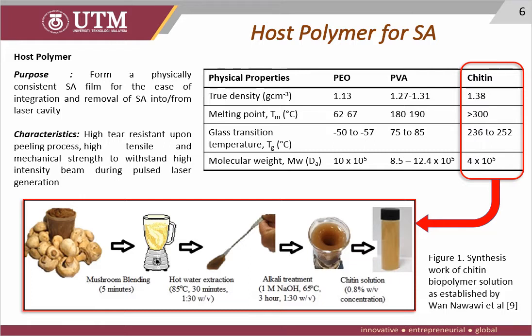Figure 1 here shows the synthesis work of chitin biopolymer solution as established by Wan Nawawi et al. The chitin is prepared from oyster mushroom. The oyster mushroom is blended for 5 minutes to increase the surface area, and then it undergoes 30 minutes of hot water extraction to eliminate any water soluble elements, followed by alkaline deproteinization for removing proteins, lipids, and alkali soluble materials. Finally, it is ready as a chitin solution.